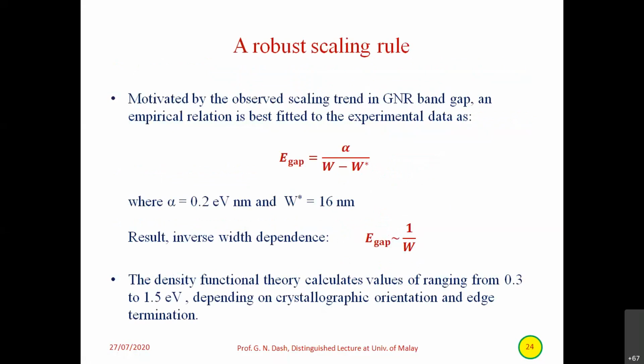If you take experimental data, then you can make an empirical relation, or scaling law, like the gap is equal to some constant alpha over width minus some other constant width, where alpha is 0.2 electron volt and W star is 16 nanometer. This empirical relation also gives, to some extent, a very accurate prediction of the band gap. The result is that the band gap is inversely proportional to the width of the nanoribbon. Density functional theory calculates gaps ranging from 0.3 to 1.5 electron volt, depending on crystallographic orientation and edge termination.